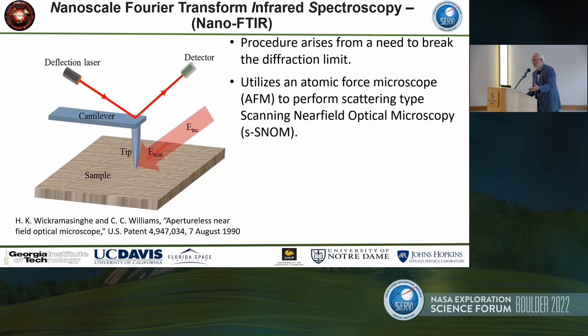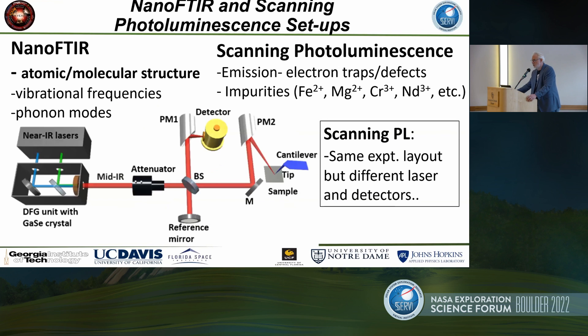The good news is that this is now commercially available — you can buy these systems. They're very good and very expensive, but you get what you pay for. You can map out the infrared vibrational frequencies with nano FTIR and get phonon modes, backing out information on atomic positions in the molecular structure. You can also run it in a different mode, exciting with a visible light laser instead of mid-IR, and look at emission spectra through scanning photoluminescence. The emission spectra arise from electronic transitions typically due to electron traps and defect sites, most often correlated with dopant ions — in particular iron, magnesium, chromium, and neodymium — and you can do this in a scanning mode too.